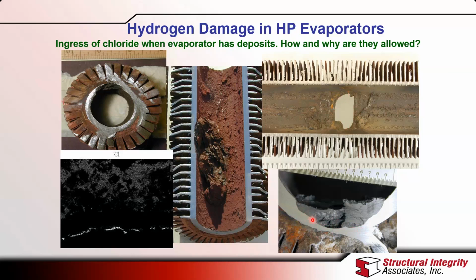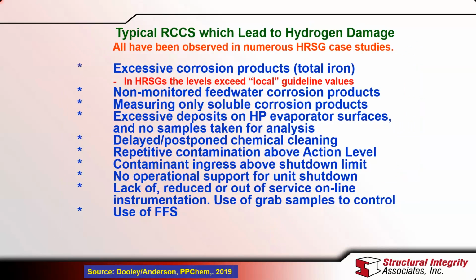And if we look at detail along this interface here between the corrosion and the metal, you'll see this light area here, which is the chloride, and the chloride is concentrated at the bottom of these deposits. It can only concentrate at the bottom of the deposits. And so this is very important. Sometimes we can't analyze this, but we know that it's there because of the mechanism. And so these are some of the typical repeat cycle chemistry situations which lead to hydrogen damage.